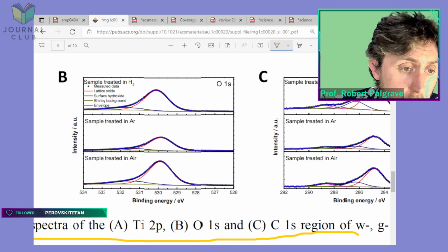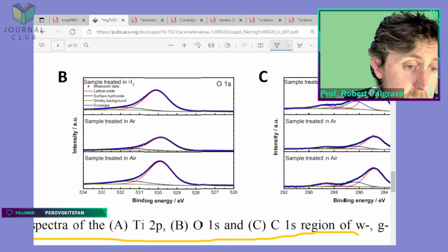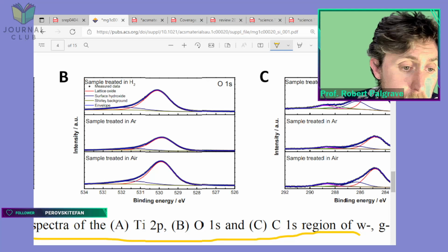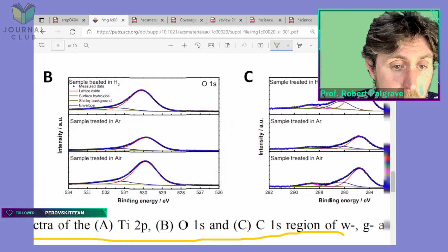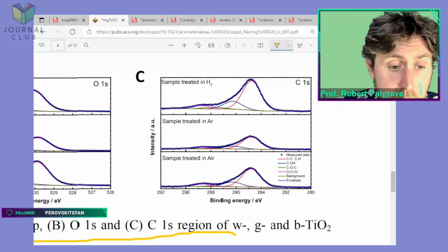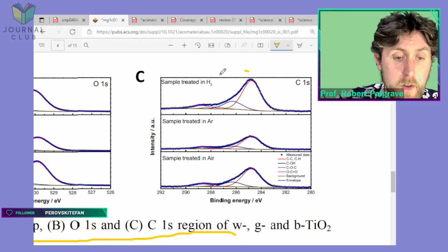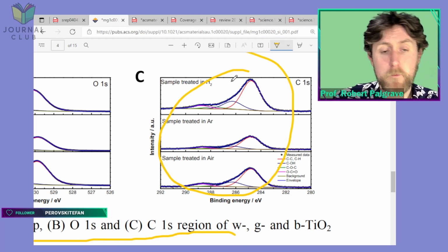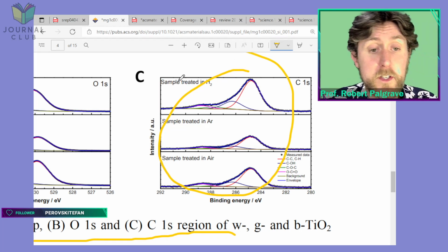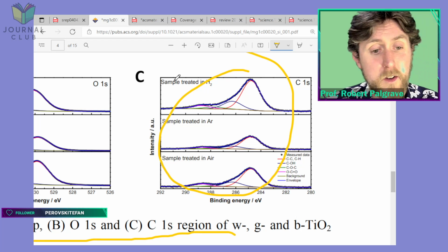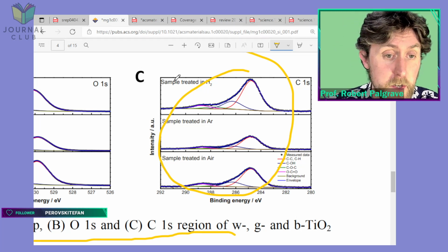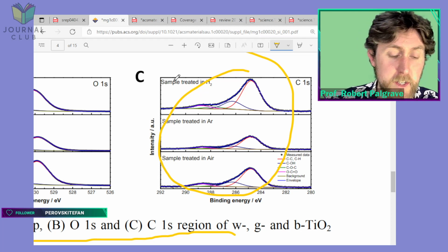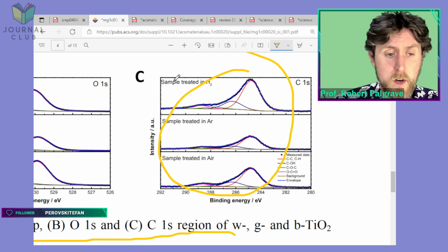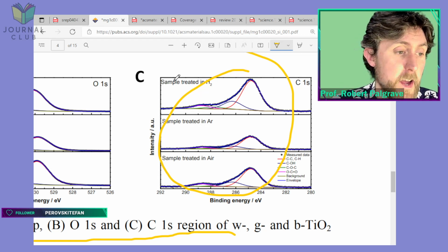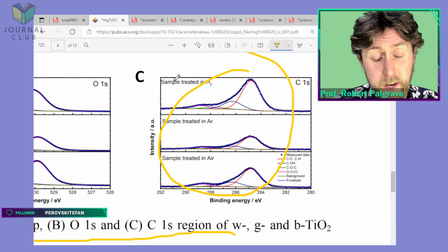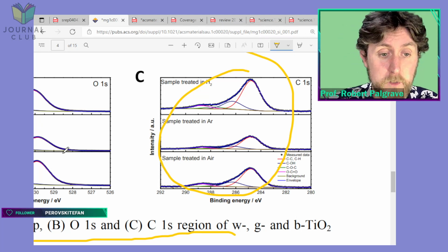For oxygen 1s, they've fitted this with a lattice oxide and a surface hydroxide, and again they don't look massively different in each of those cases. And the carbon peaks, again, this is a pretty typical carbon spectrum from just contamination from surface carbon that you get on the surface of these things. Again, it doesn't really look like it's changed much. I'm kind of surprised that at 400 degrees treated in air, they didn't burn off some of that surface carbon, unless of course it's contaminated after the annealing process. Actually, that's probably more likely, isn't it? It's probably contaminated after the annealing process.